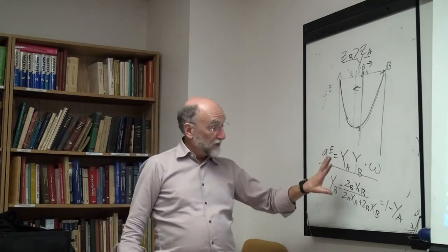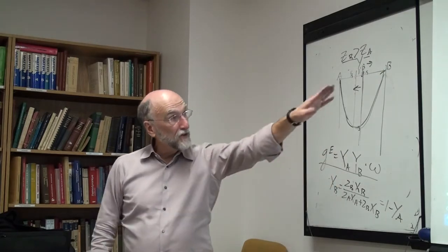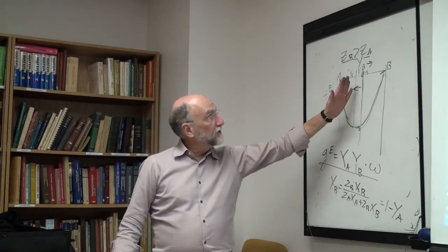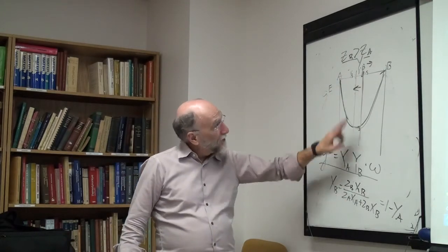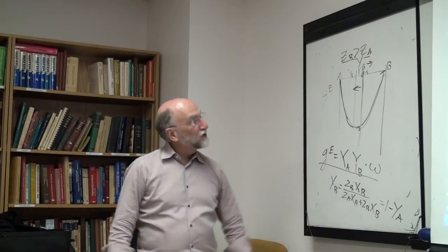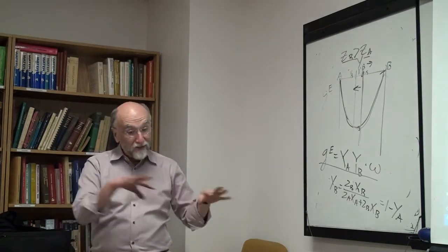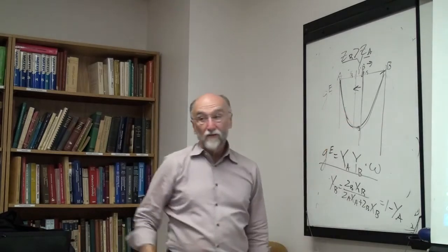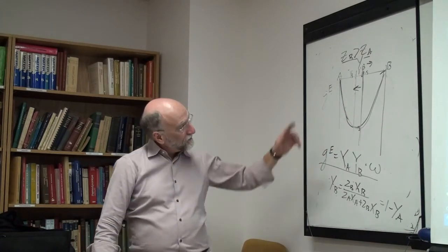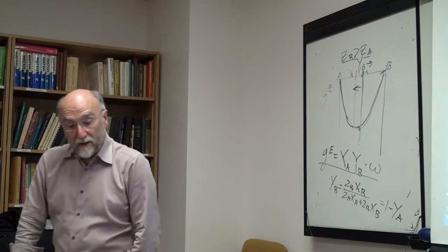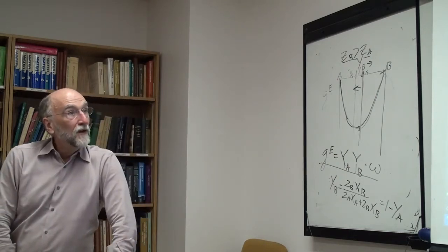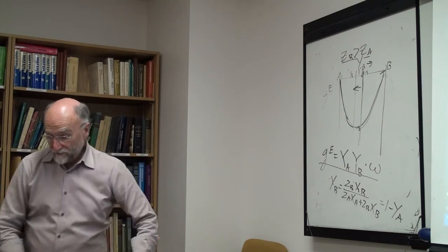And this is just in the Bragg-Williams way, because you're using the limiting case of the Bragg-Williams model, but you're using the fact that the peak is being shifted not because the bond energies vary with composition, which gives you this sort of thing, but because the coordination number varies with composition. And this doesn't work in solids, but in many liquids it has been shown that that's what's happening.